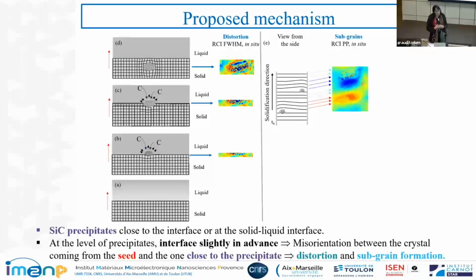So with all these results, we propose a mechanism for the formation of these defects during solidification. Due to the low solubility limit of carbon in silicon, you have the precipitation of silicon carbide during solidification, close to the interface or at the solid liquid interface. Then at the level of this precipitate, the interface is slightly in advance compared to what it's going from the seed here. And you have the formation of these distortions of the crystal. And at the same time, because you have several of these precipitates all along solidification, we characterize them everywhere in the sample, you can have the formation of these